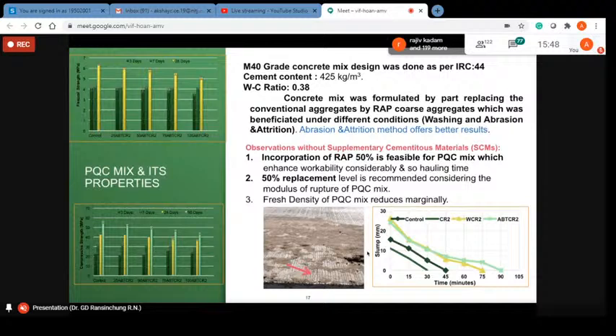So now what is that? The desirable modulus of rupture, as per MoRTH clause 602, says that the concrete mix which is capable of producing at least 4.5 MPa modulus of rupture is suitable for the construction of rigid pavement. So as a result, the basic target is to achieve this minimum 4.5 MPa modulus of rupture.